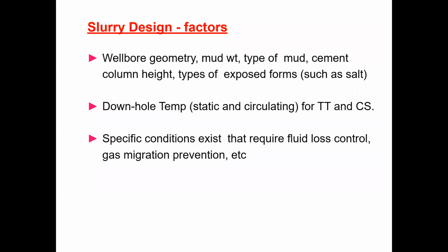If that is more, then during the pumping and displacement of the cement, when it enters into the annulus, the excessive water may be lost to the formation and the slurry may become thicker. You will not be able to displace. That's called bridging. Bridging can be caused if excessive water is lost. So we need to control the fluid loss.